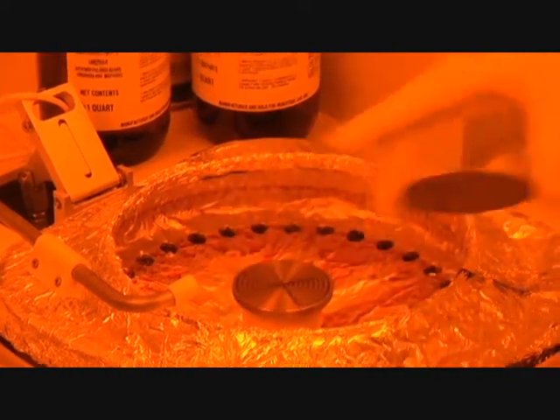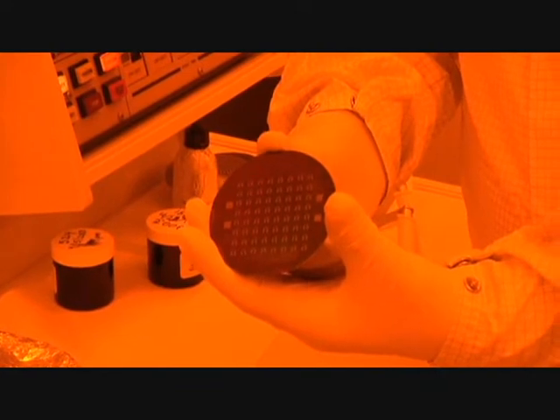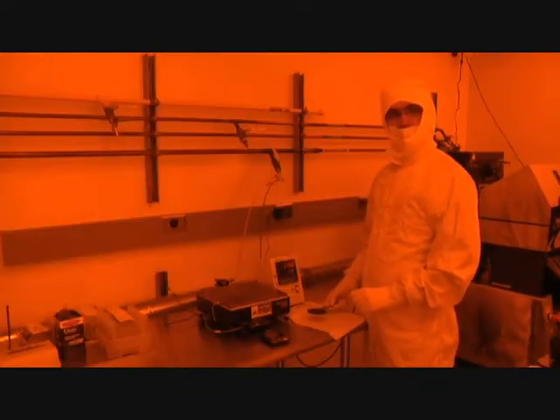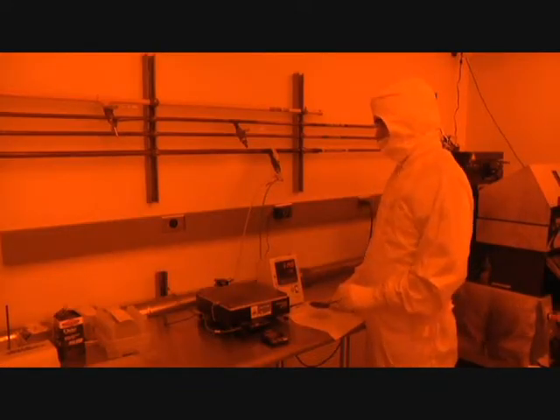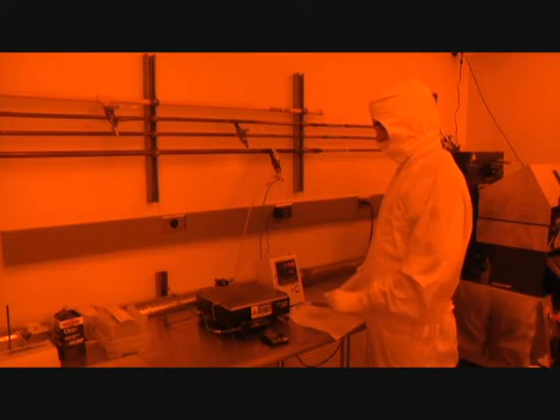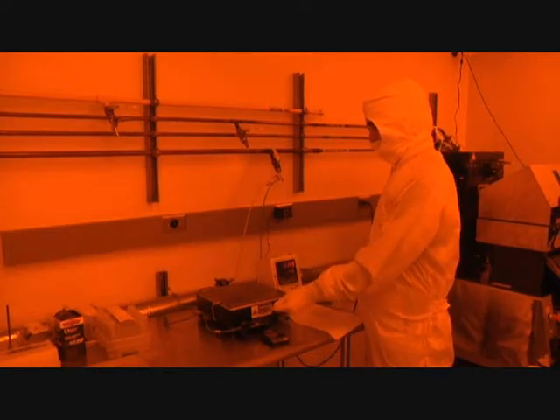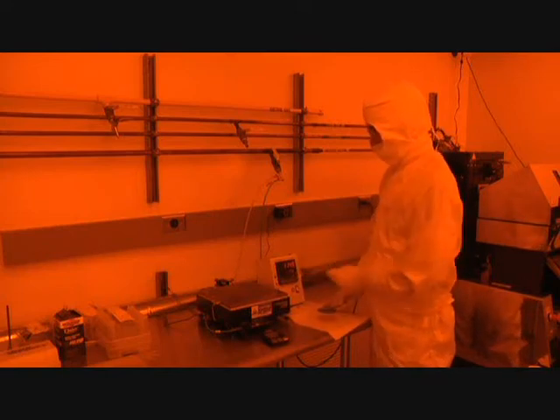And there you can see the wafer right after the spin, but before it's been baked. Now that the wafer has been spun with photoresist, we need to bake that photoresist to drive off some of the solvent and to make it essentially a solid instead of a liquid. We're going to do that using a hot plate that's been set to 115 degrees C.